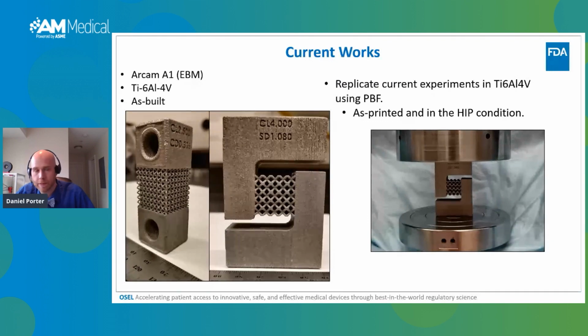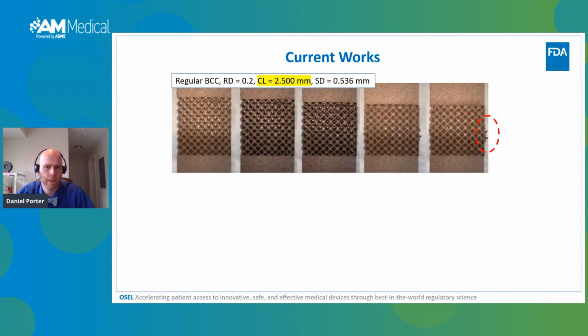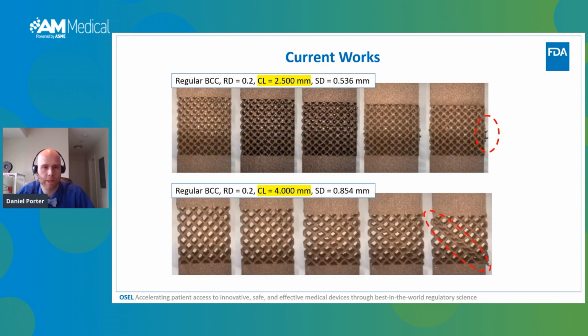We're going to repeat the same experiments, currently and in the future. We're going to print these lattice specimens in a Ti alloy using an e-beam machine. We're going to test them in the as-printed and HIPed condition. We're probably not going to do tension tests on these. We're probably going to substitute some fatigue tests, so we're going to do some fatigue compression on some of these samples. And here's just a quick taste of what we're doing now. We don't have a lot of these samples. It's just a preliminary experiment.